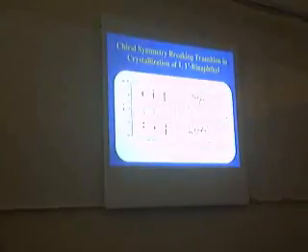And there's no size dependence. This x-axis shows the weight of each crystal phase taken up from the melt, and the y-axis shows the enantiomer excess of each crystal phase, and it shows that the enantiomer excess is not size dependent. So it means that when crystal growth occurs, the enantiomer excess of the crystal growth point is kept almost constant.